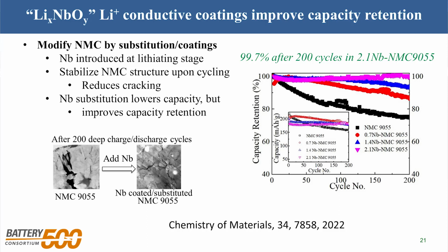How does it save it? Well, it turns out it basically cuts down on the cracking. So it modifies the mechanical behavior of those primary particles so they don't crack. So you can see on the left-hand side there's 90% nickel. No niobium, you can see big cracks. On the right-hand side, the cracks are much smaller and doesn't degrade the material. If you get big cracks, then the electrolyte goes into those cracks, forms another surface film there, and increases the resistance.